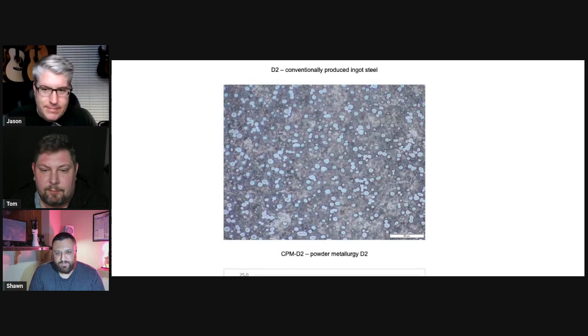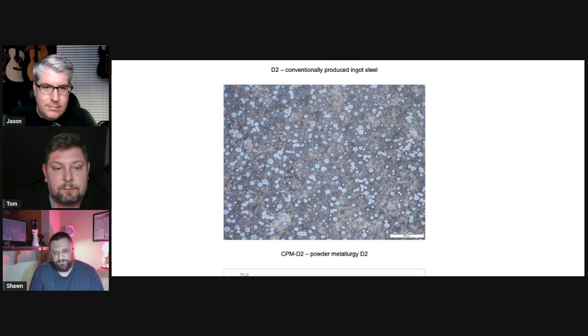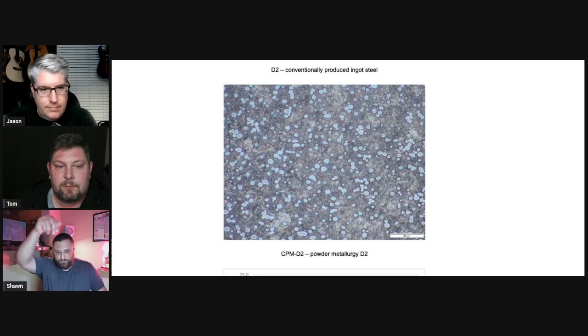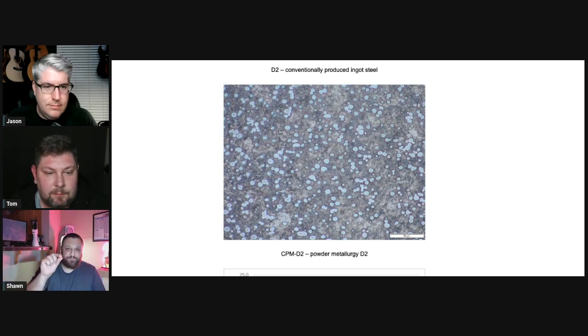Yeah. So instead of taking the steel and just cooling it, basically from molten steel and pouring the ladle into a shape, like a big square to make a big billet, they actually take the steel, and it's a very fancy process where they atomize it like a little spray mister. And each little droplet is like its own ingot and cools. And then all the steel particles solidify when they have gas blowing as it's going from molten steel through an atomizer, with each little droplet becoming an individual ingot.